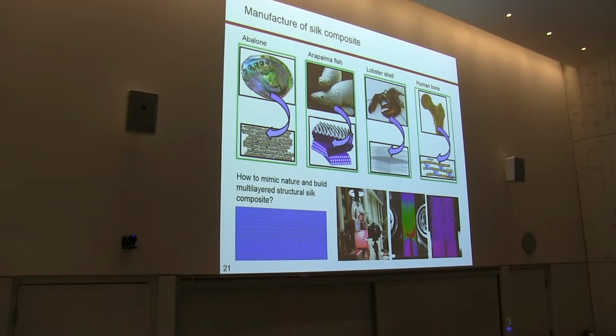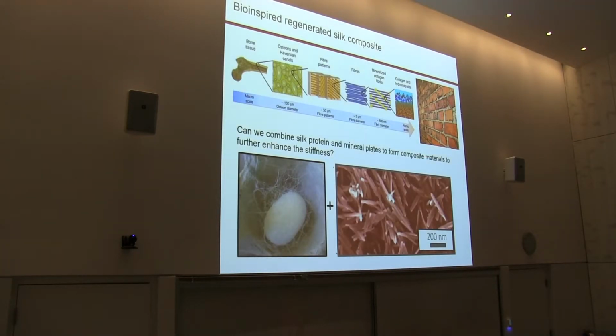So I directly developed that kind of brick and mortar geometry by combining some soft material and stiff material together. And then once I create a crack and load it, it doesn't crack straight through the material, but it diffuses the deformation energy everywhere to make it tough enough. But 3D printing is good for demonstration. To synthesize the actual material, I need to follow nature and design some chemical synthesis process to make new material.